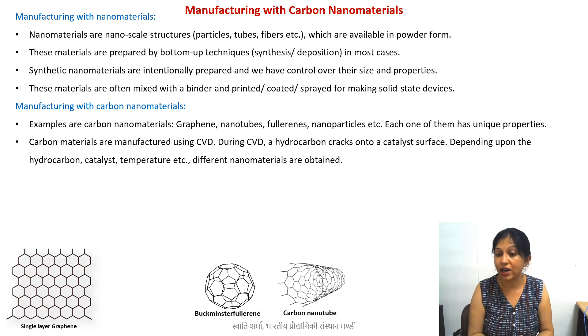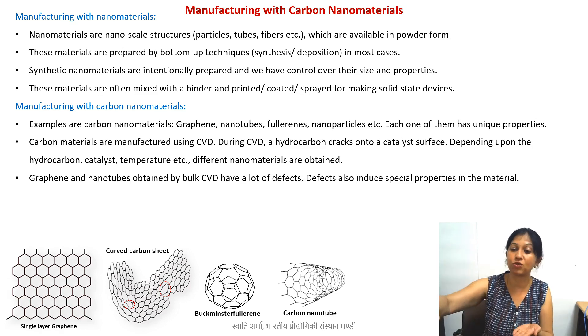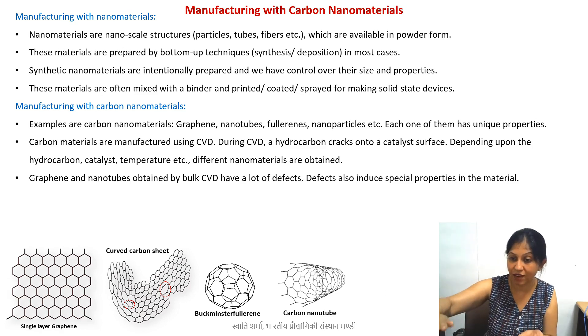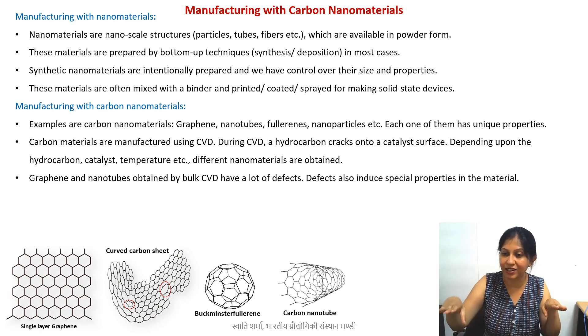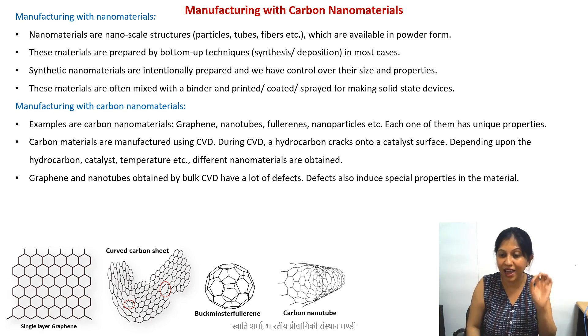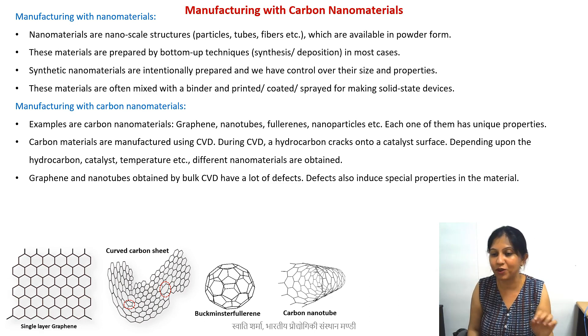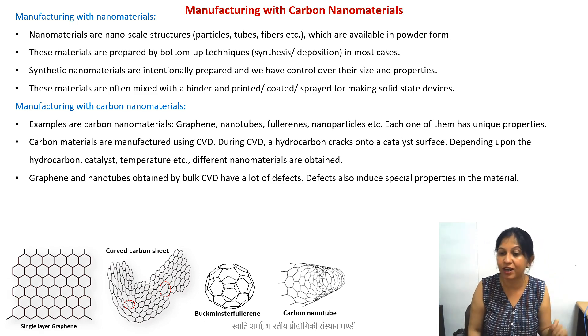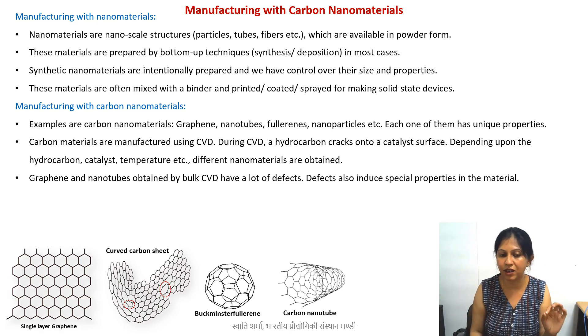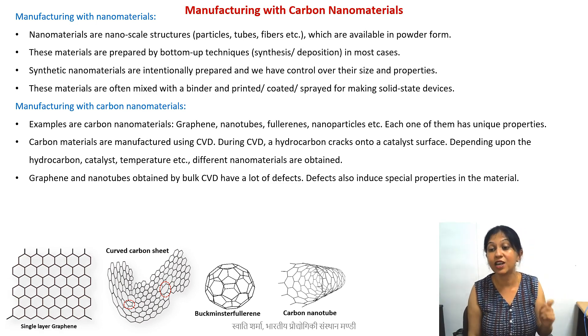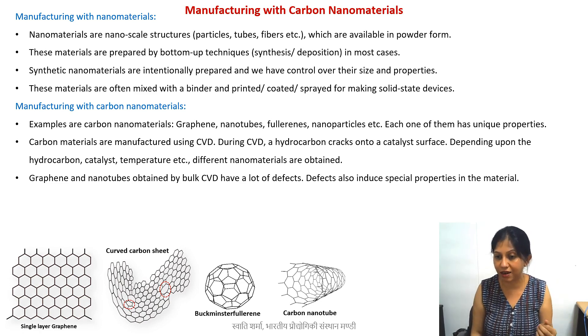When doing CVD or any other synthesis method, you will always have some non-six-membered rings. When you have a seven-membered ring in a sheet that should only have six-membered rings, you will not have the same flat structure — it will bend slightly. The hybridization also changes: only in perfect graphene or graphite do you have pure SP2 hybridization. Curved sheets result from five- and seven-membered rings and other defects. This is why I refer to it as a curved carbon sheet rather than a curved graphene sheet.